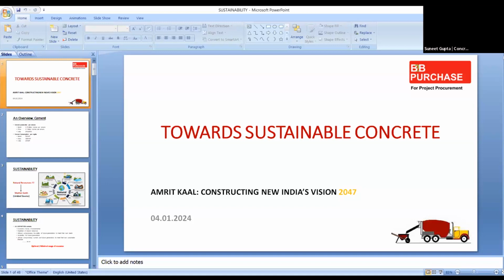And reducing the clinker factor. Obviously, when we make clinker, we use limestone. And to reduce limestone, obviously the consumption of clinker in cement production has to be reduced. Earlier it was only OPC cement, what we call ordinary Portland cement, where we used to have 90% plus clinker. Now we have started making Portland Pozzolana cement and Portland slag cement. This third one is Portland slag cement, where the clinker has been reduced quite effectively, as you can see from the pie chart.